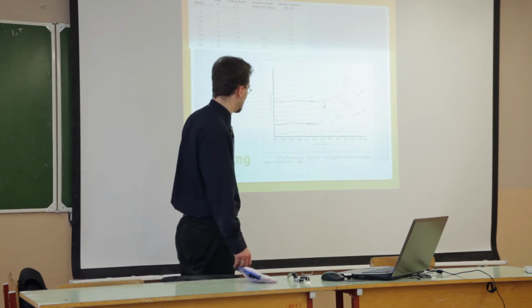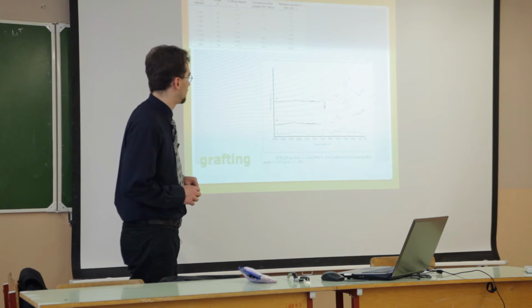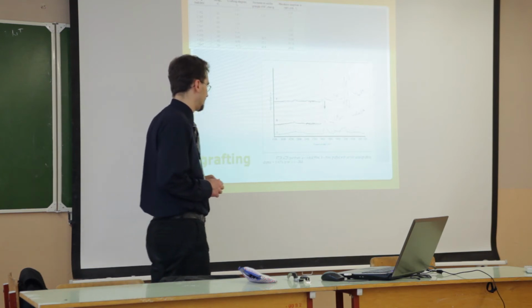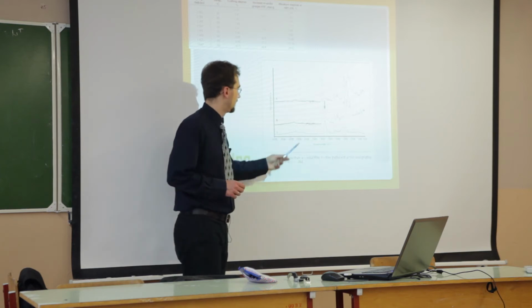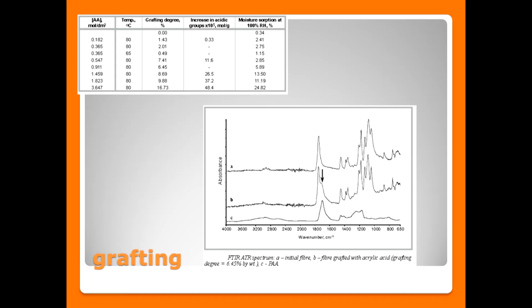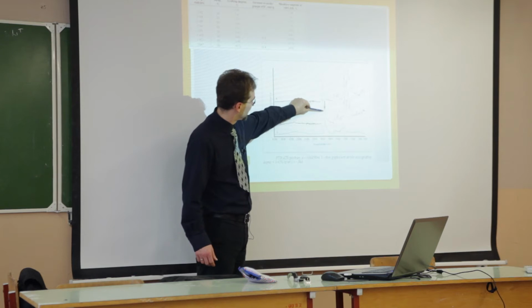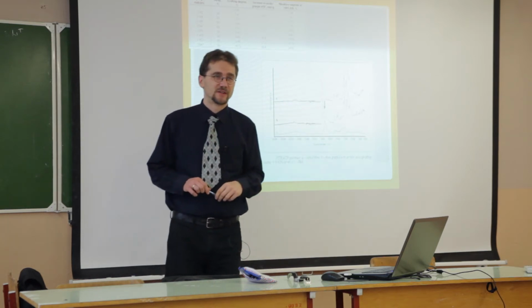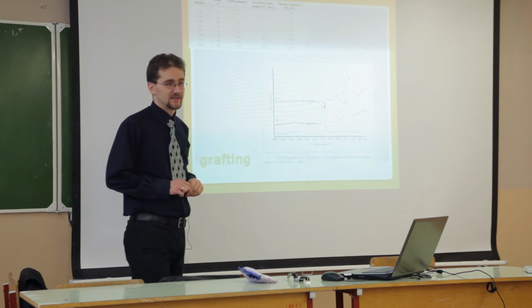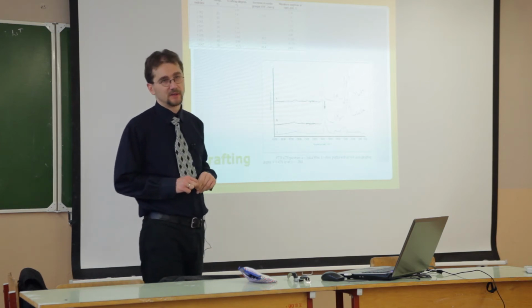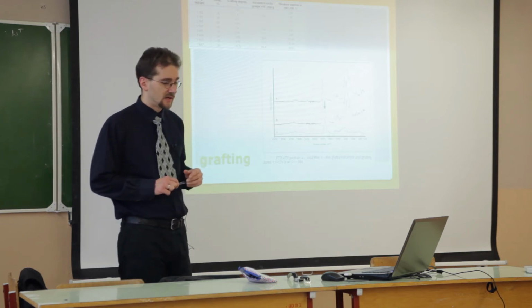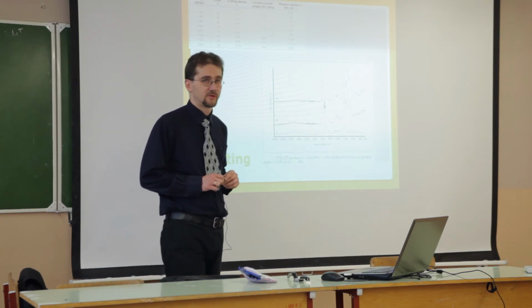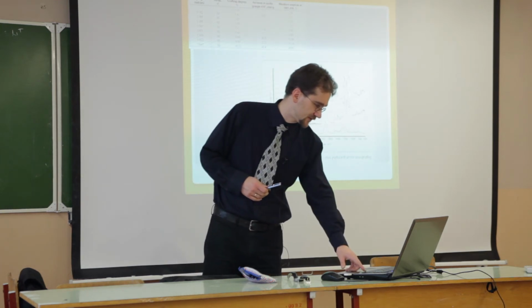Here you can see A, the initial polylactide fiber, B, the grafted fiber, and C, polyacrylic acid. You can see a strong signal connected with the carbonyl group from the acid. I know it's probably not easy to see from the end of the room, but believe me, here we can see the signal connected with the carbonyl group from the polyacrylic acid. So FTIR spectroscopy can be a good technique, if you have such a device, for controlling the grafting process.